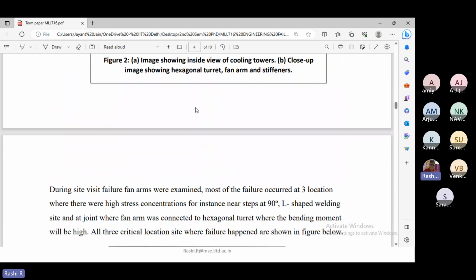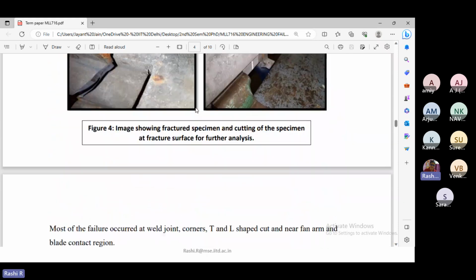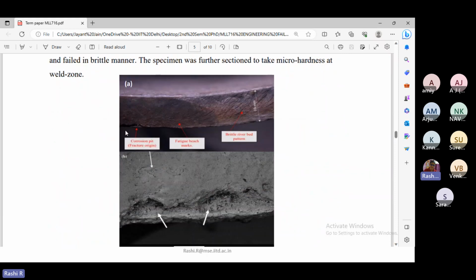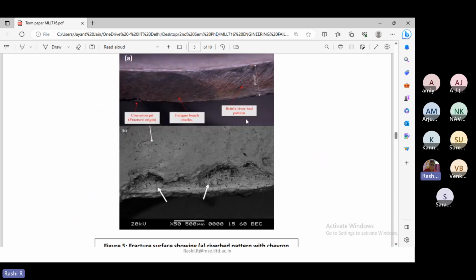And when you saw the microstructure of the material, you could see a corrosion pit where the fracture started originating, and because of the varying stresses, the fatigue beach marks were observed. And then once it reached enough crack length, it failed in a brittle manner, and you can see the failure in a brittle river bed pattern. And when further seen in the corrosion, the pits were observed like this.